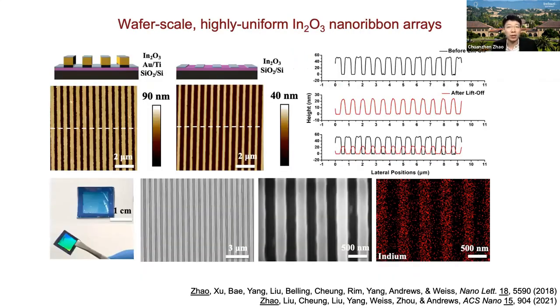Here are our results of the patterned indium oxide nanoribbons. Those two are atomic force microscope images of the topography of those nanoribbons before and after the metal removal. I was super excited when I saw those and compared those patterns, as they overlap quite well with each other. As you can see from the height profile here, we have a very perfect, almost perfect control over the nanoribbon sizes.